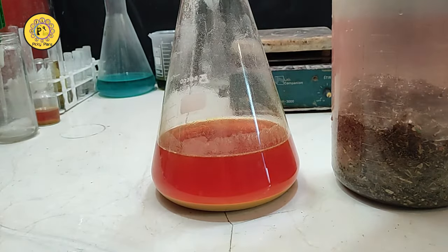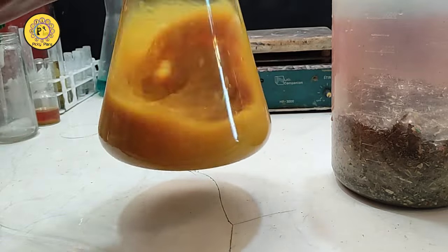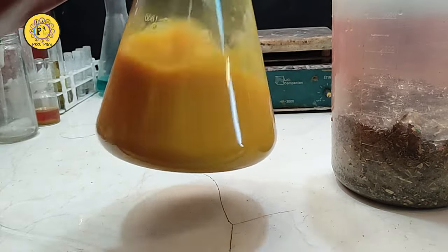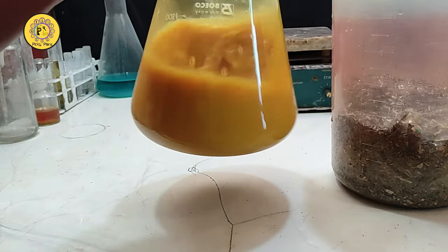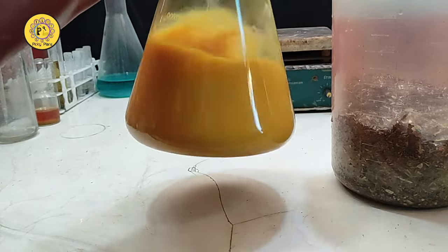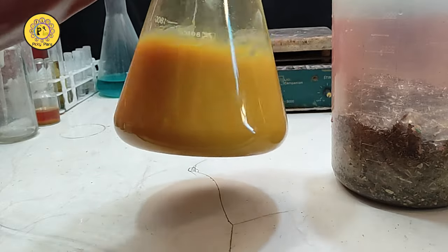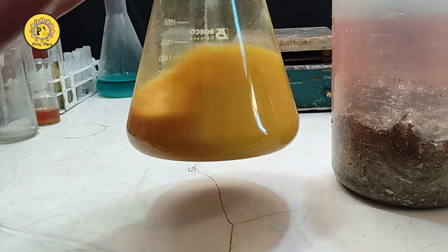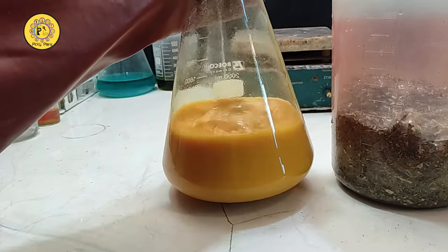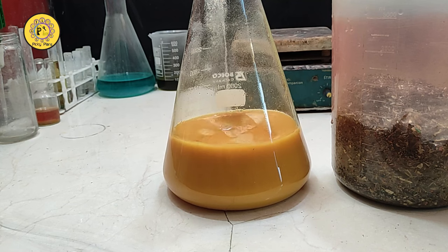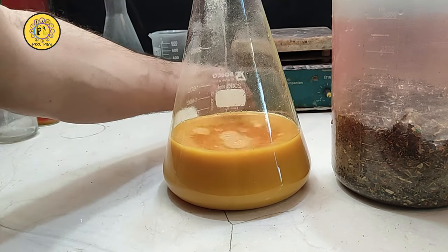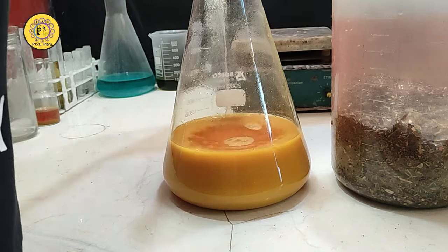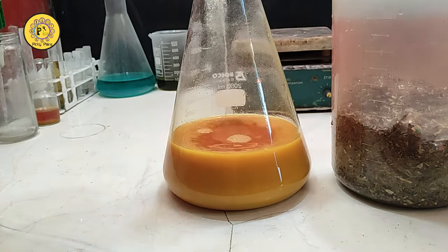And also let's rinse the powder stuck to the walls and twirl it to dissolve as many components as possible. Stirring is needed for about 2 or 3 minutes occasionally. And after that, you just need to let the powder settle down and decant the solution.